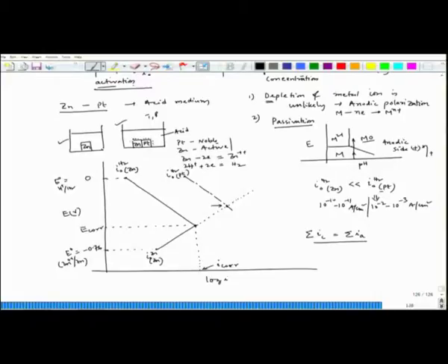Now, here we have two sets of cathodic reactions, one on the zinc surface, another on the platinum surface, and one set of anodic reactions. So this is two sets of cathodic and one set of anodic. Zinc is dissolving from the zinc surface only; platinum would not dissolve because it is a cathodic component. Since there are two cathodic reactions, in order to fulfill this criterion, the total cathodic current density should be equal to the total anodic current density, so I should add up these two polarizations.